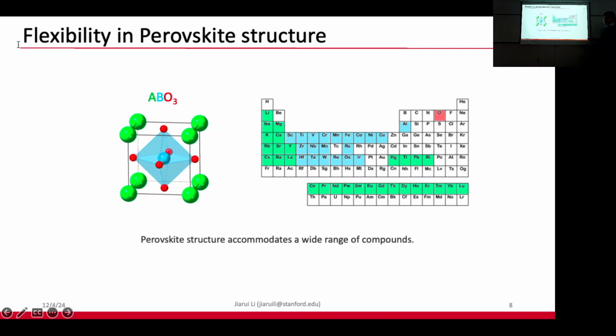As a very good example, a lot of these 3d transition metal oxides are in the perovskite structure with the chemical formula ABO3, where the major player in this structure is the atom in blue, the B atom, which sits at the center of this BO6 oxygen octahedron. The reason that a lot of materials are in this perovskite structure is that it has a lot of flexibility in hosting a large class of elements on the A and B sites.